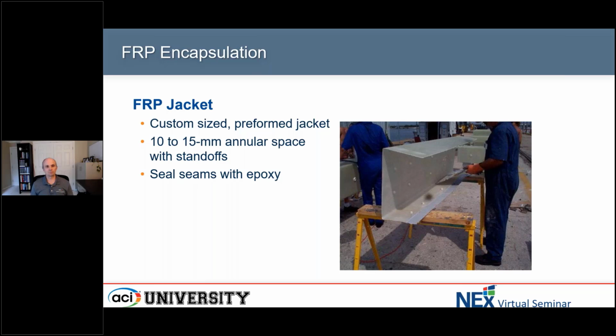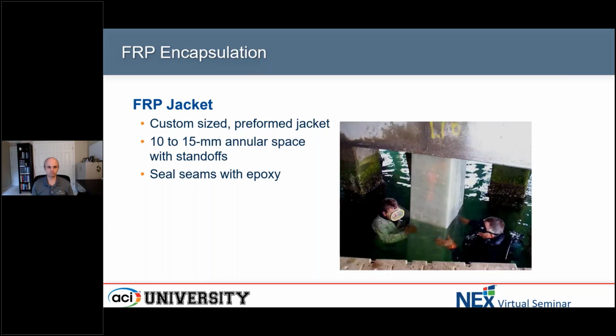They're usually prepped above the water with adhesives on the seams to bond the forms together as you place them around. The adhesives that are used are marine grade materials. Typically, they're designed to be used underwater and designed to cure underwater. So these are specialty types of usually epoxy adhesives that are used to do this. And then these are simply placed around an existing structure, as you see there, usually using divers, just depending on the application, depending on the depth that these things need to go.